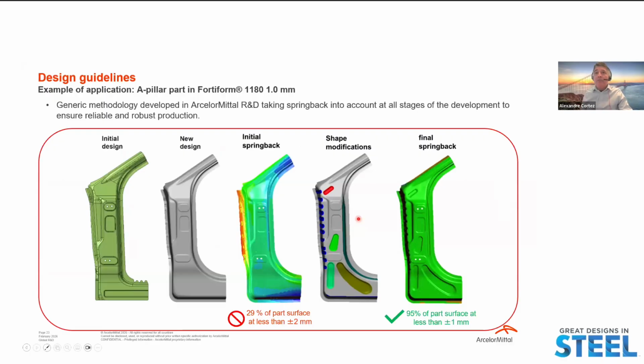Here is an example of this generic methodology developed by ArcelorMittal, taking into account the spring back during the part development stages. This is an A-pillar part with Fortiform 1180 1.0. As you can see here, this is the initial part without any features implemented yet. Then we add some implementation in the flange over here and made the initial spring back simulation, and the spring back is still in the part. Then some shape modification was done in the sidewall, adding some embossments. Then we made another simulation step to check the final spring back. It achieved 95% accuracy in the part dimension.